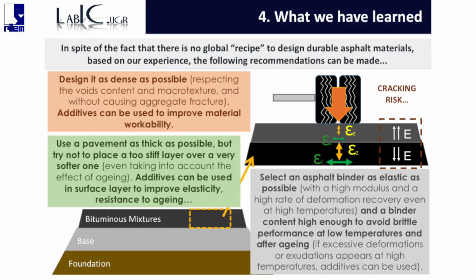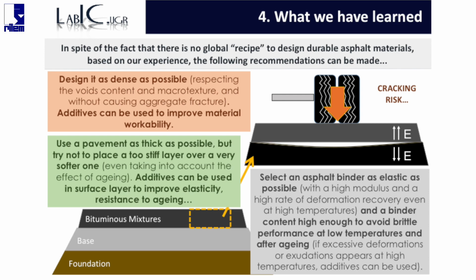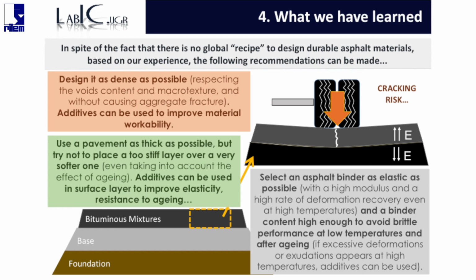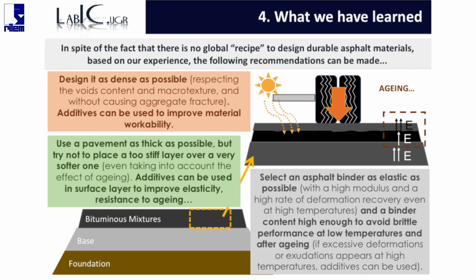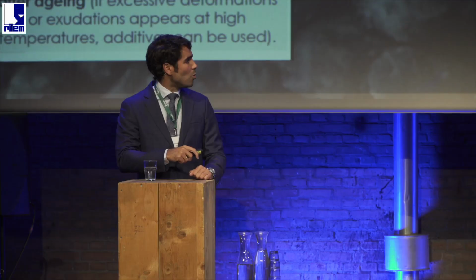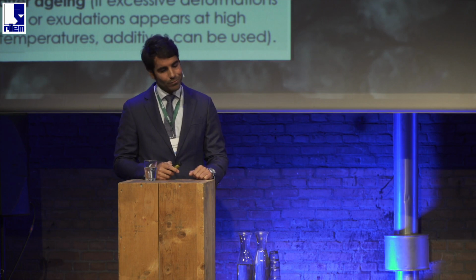If we use a very stiff layer over a softer one, the problem that we can have is that the deformation in the bottom layer can be higher than in the top layer, so the deflection becomes higher. The top layer cannot go with the bottom layer, and it will crack. This phenomenon also happens when we have aging. When aging comes, the stiffness of the bottom part of that layer becomes much stiffer, and then this type of cracking appears. For this purpose, we can use additives in the surface layer to improve its elasticity and resistance to aging.